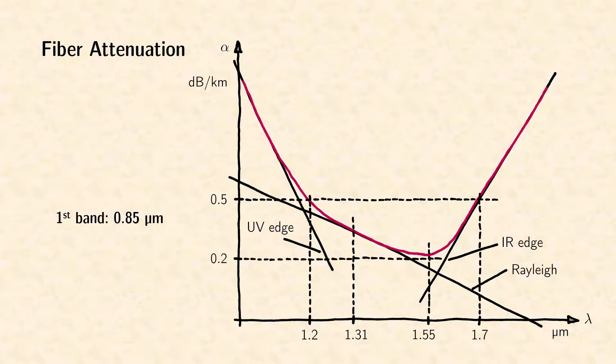With the advent of indium gallium arsenide phosphide laser diodes, data communication shifted to 1.31 micrometer. This second communication band was located in a local attenuation minimum. The origin of this local minimum was contamination by a small amount of chemical OH groups in silica fibers at these days, which resulted in a certain absorption band. Current silica fibers show no OH absorption band anymore.